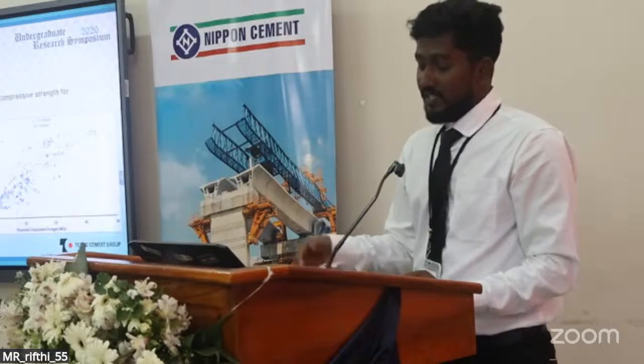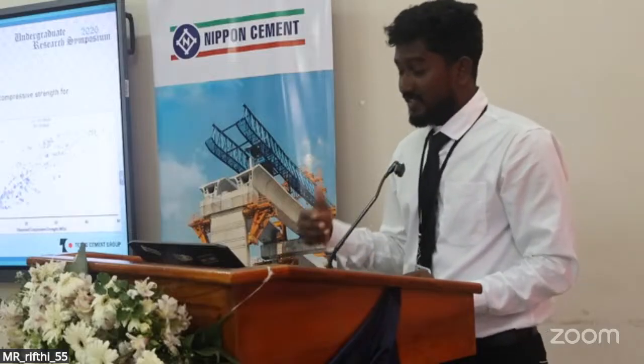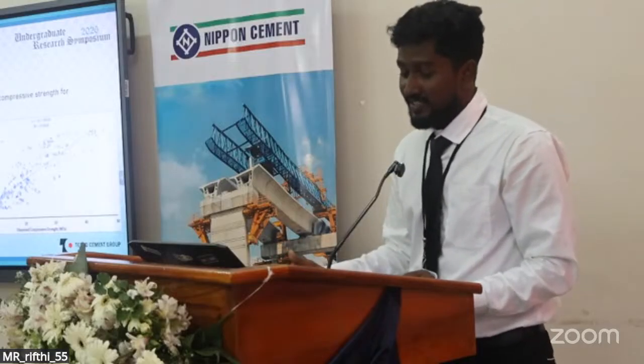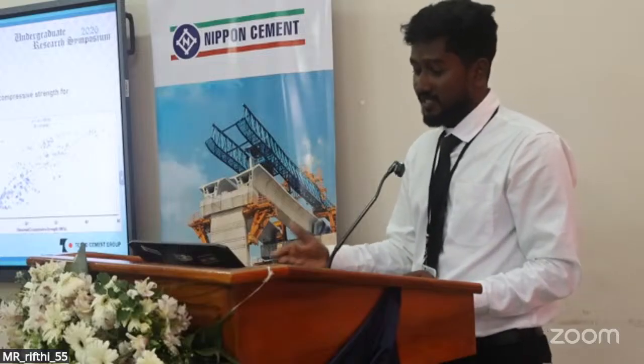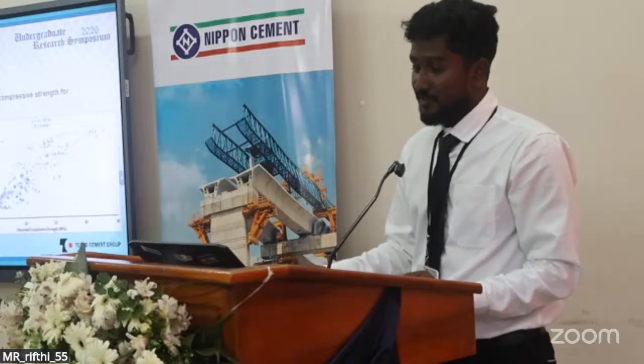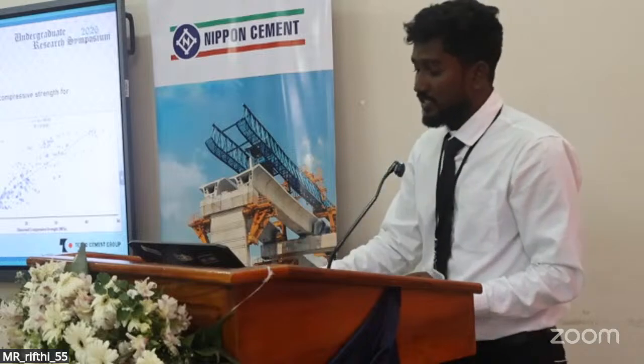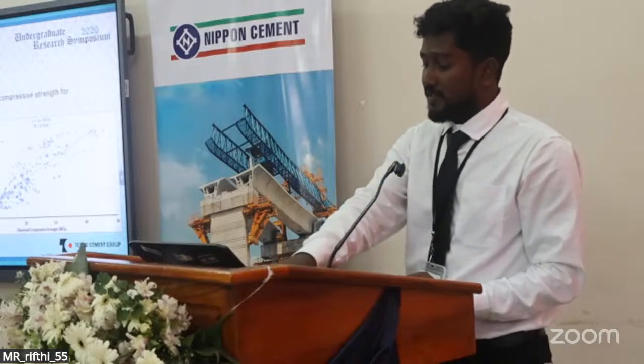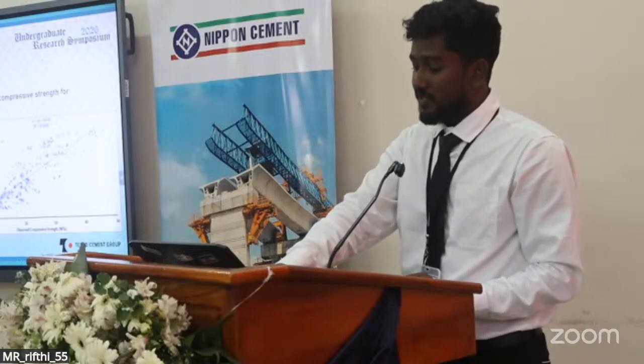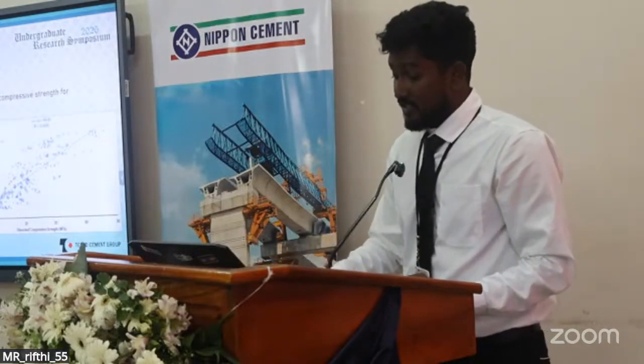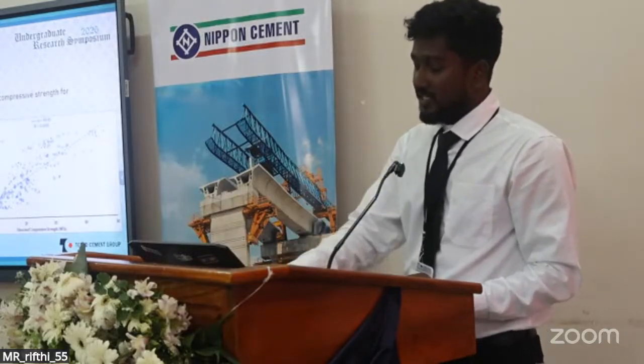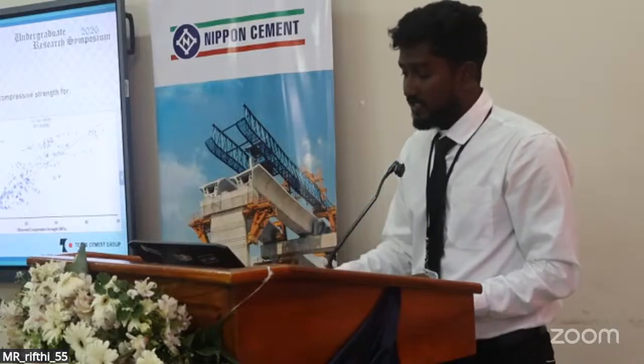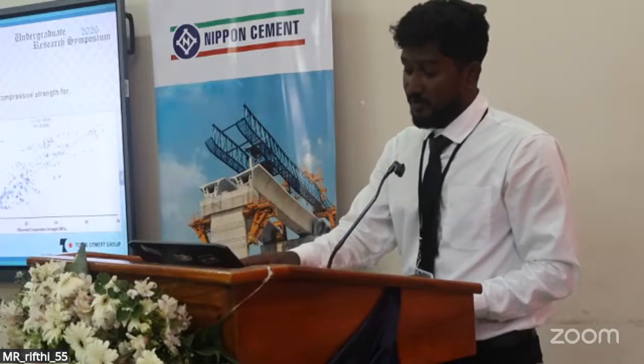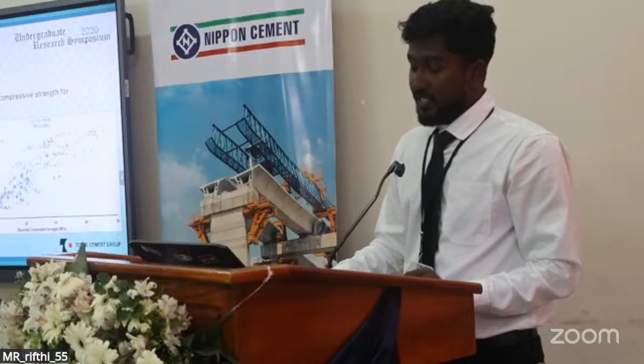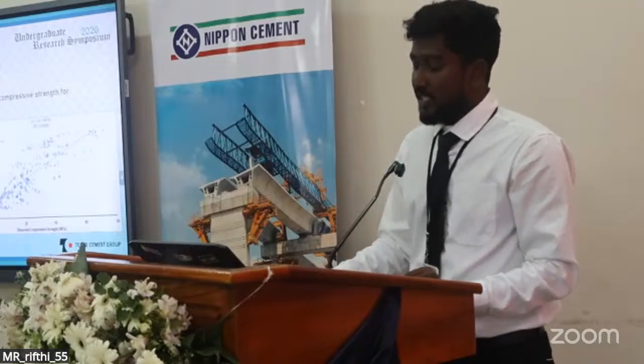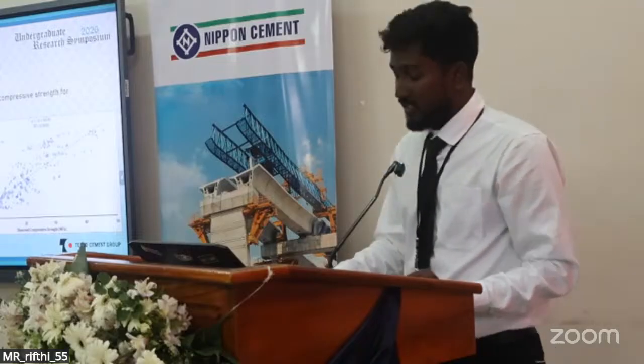Then after that we update the equations from the literature review. This equation I get from the literature. From that we predict the compressive strength and plot it against the observed compressive strength. According to that we get the accuracy 0.46, 0.64. Then here we use the parameters as porosity, aggregate, cement and compaction in the study.